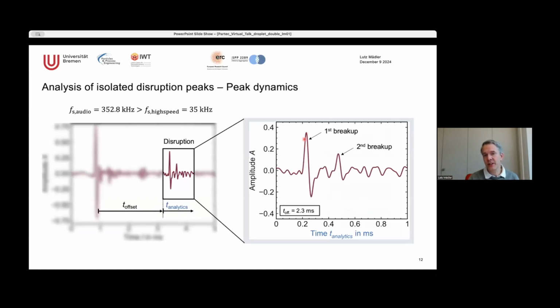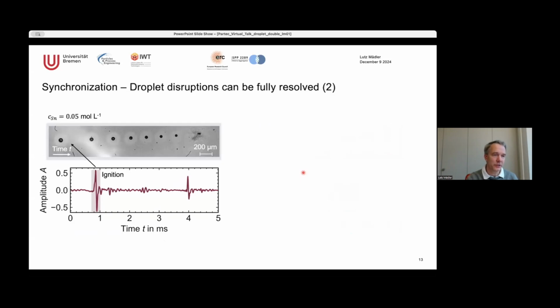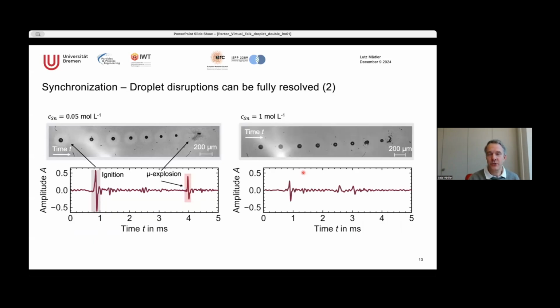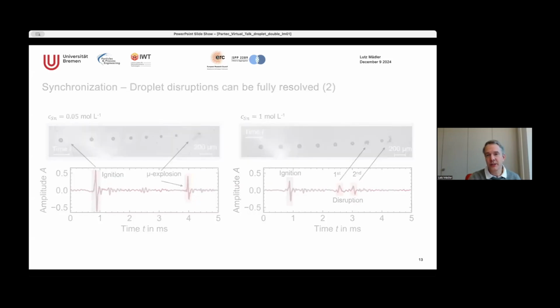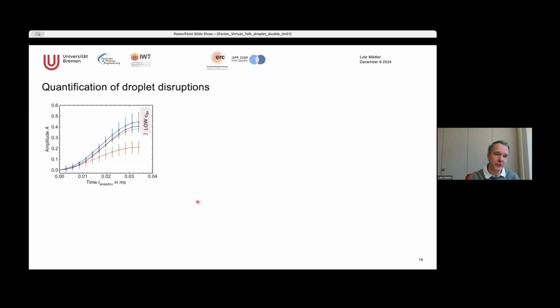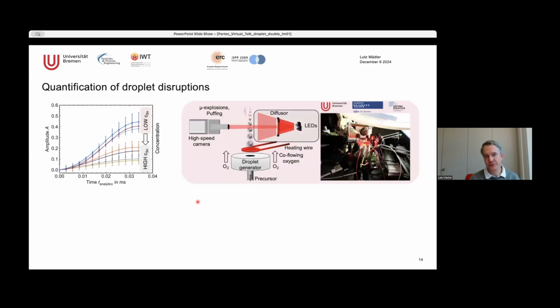And basically, this gradient is a measure of how fast and how violent this explosion is. And this is what Arne is looking at. He looks at the violence of the explosion and tries to characterize and categorize explosion events. And you see that it looks different here and here, and you also see different signals. He's been pretty successful in looking at these events and categorizing them. And he could trace that back to the concentration you have in the droplet. And once we know that, we can, so this is one of the setups he's using, we can actually look even closer into these droplets.